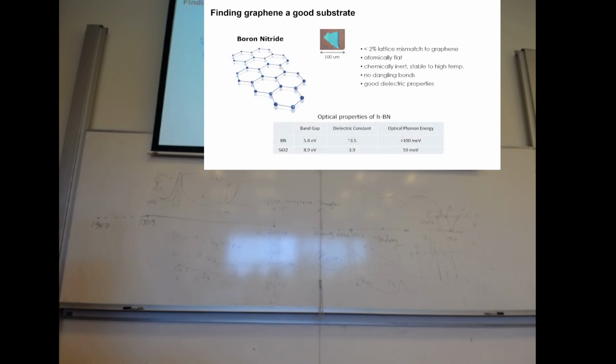And here's another way people found, instead of getting rid of the substrate, which is very sophisticated and the yield of sample is very low, it's not very practical, not everyone is happy using that kind of technique, and it's fragile too. So there is another way. Like Dima said, if he was at the time of 2010, he would try some substrate to replace silicon oxide, because we saw that silicon oxide has a lot of roughness and dangling bonds.